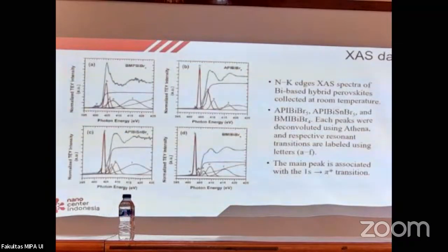Yeah. So now we go with the XAS. Here, I said it's element sensitive, so we look at the nitrogen element. All the chemical structure has a nitrogen. So the first thing that we need to understand is we collect the information at room temperature. And then what we found is that the phenomena comes from the fact that we see the main transition line that goes very sharp. But if you look more carefully, for the neighboring class, the API system, you have a very distinct state here. This thing is associated with the 1s-π orbital.